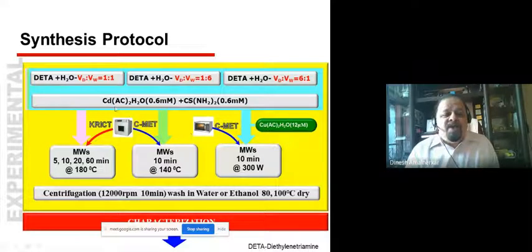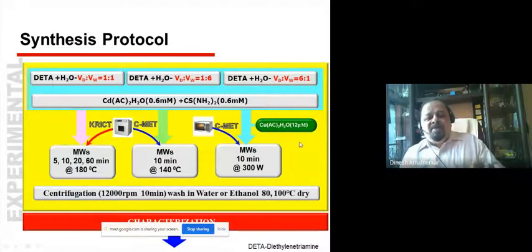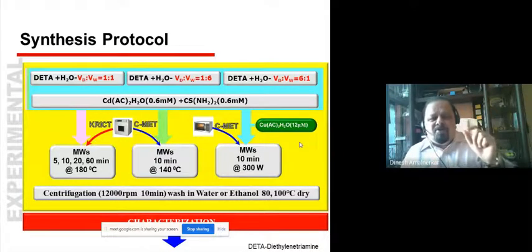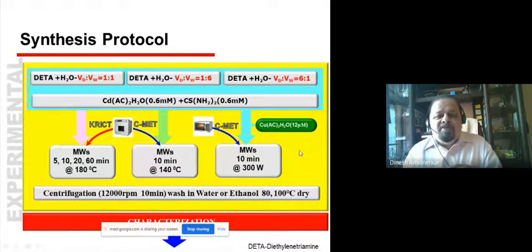He has taken, in a typical reaction protocol, cadmium acetate and thiourea in a certain molar ratio, and mixed in a binary solvent system of diethylenetriamine and deionized water in a certain volume ratio, this time with the addition of copper acetate in a certain molar concentration. The resultant mixture was placed in a Teflon-coated autoclave, just a small quantity, which was placed in the normal household microwave oven. That's why I call it kitchen chemistry. We have a pressure cooker, we also have a microwave, and let us see whether we could get results.